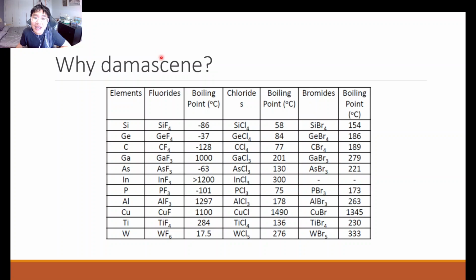Okay, so why do we need a Damascene process for copper? This is simply because copper does not have any suitable etch chemistries. Whereas for aluminum, if we use a chlorine based or bromine based etchant gas in the plasma chamber, the etching byproducts are things like aluminum chloride and aluminum bromide. These are relatively volatile gases at the temperature of the plasma chamber operation, so they can be diffused away, successfully removing the aluminum from the wafer surface entirely.